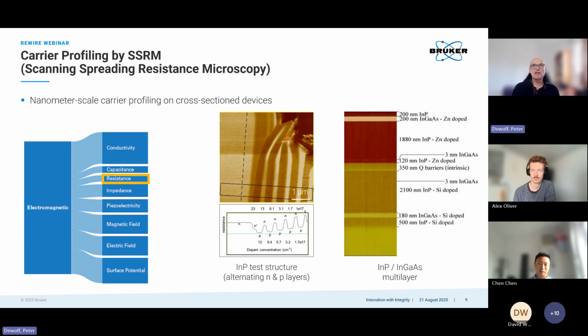This one is actually indium phosphide, so more of a small bandgap semiconductor, but similar technique. I like these examples because first they illustrate spatial resolution - some of these layers here are only a few nanometers in size and they can be resolved. These are again cross-section devices.